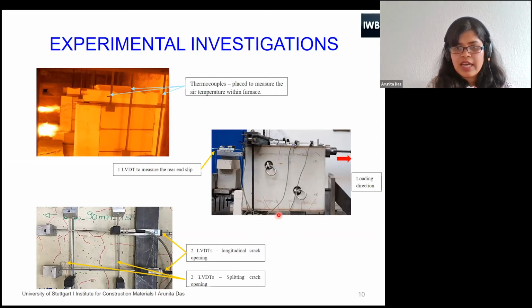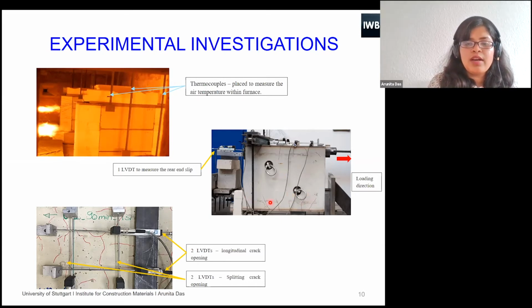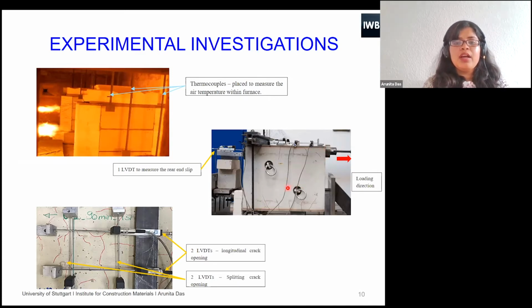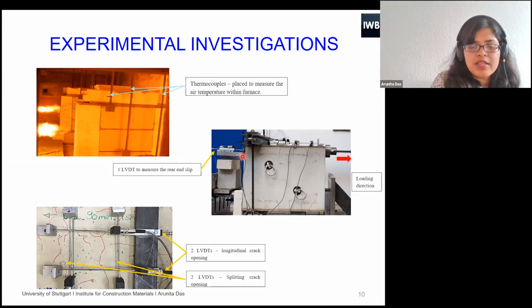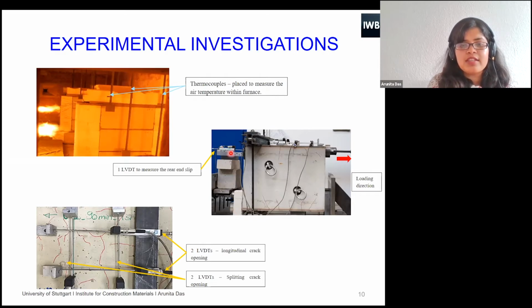You can see these red lines, which are the cracks generated due to fire inside the furnace. Here on the top also you can see. In order to make it a little bit economical, we have installed two rebars in one beam and test specimen. At the bottom there is one rebar, and at the top there is one rebar, but there is a sufficient distance so that there will be no effect of one rebar on the other. This is the rebar which is getting pulled in this direction, and this is the rear end of the rebar where one LVDT is installed to check the displacement.